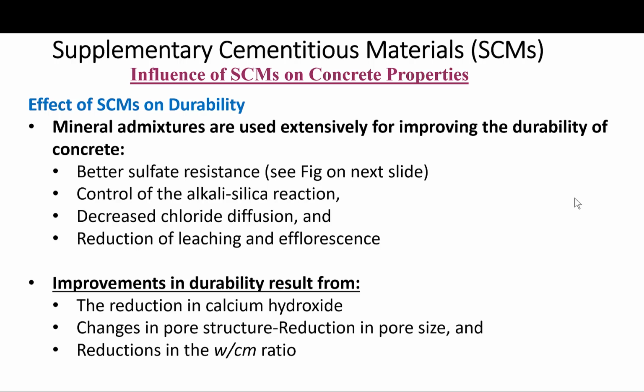This is because we removed the calcium hydroxide in the pozzolanic reaction. Improvements in durability result from the reduction in calcium hydroxide, which is the most soluble of the hydration products, also from changes in the pore structure, and reductions in the water to cementitious material ratio. All three factors combined result in improved durability and changes in pore structure.